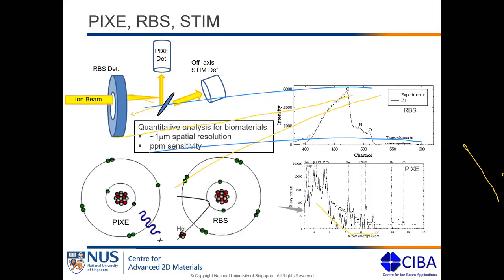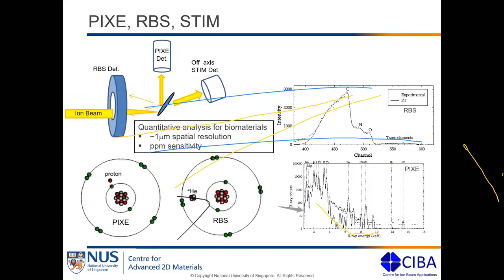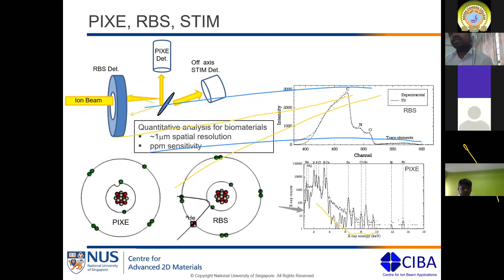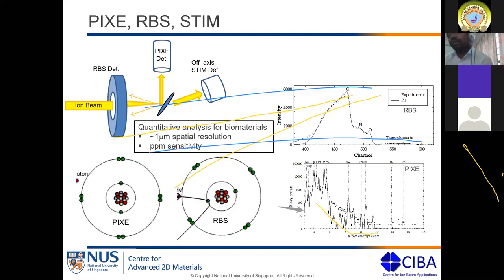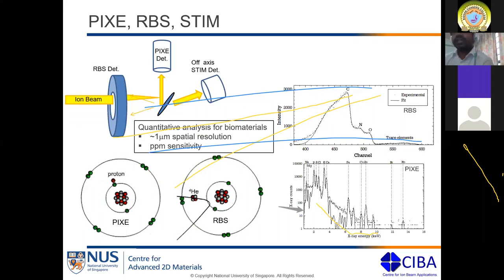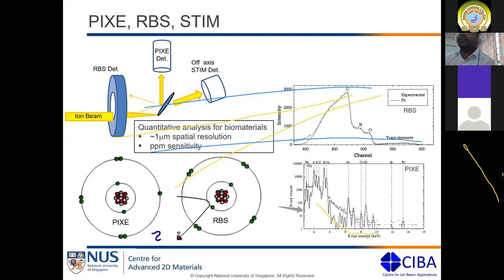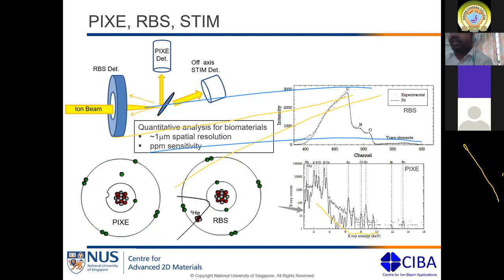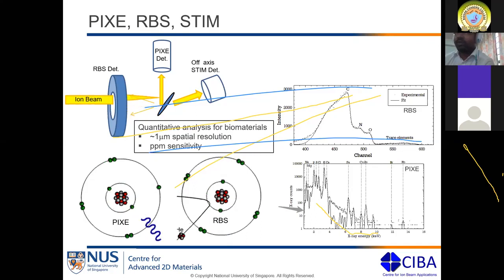And these X-rays are coming out because of the interaction of the ions and the electrons. When the electrons from the core shell of the atom are knocked out and the higher shell electrons jump into these lower orbits, then you will see emission of X-rays. And those X-rays are detected with this PIXE detector. And from there, this spectrum will be the fingerprint of a particular element in that material. So you can do elemental analysis using that.